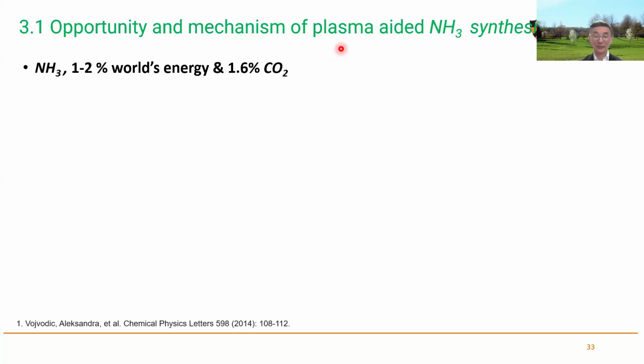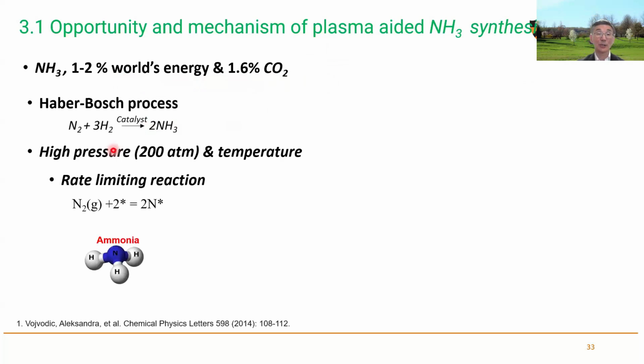enhance ammonia synthesis. Ammonia contributes probably close to 2% of CO2 emissions. And ammonia catalysis requires high temperature, high pressure, typically 200, 300 atmospheres. The temperature typically is 500 C. It's very energy intensive. You have to compress it to high pressure, you have to raise the temperature. And the rate limiting reaction is nitrogen surface adsorption and dissociation. Can we do ammonia synthesis at 1 atmosphere pressure at room temperature with plasma?